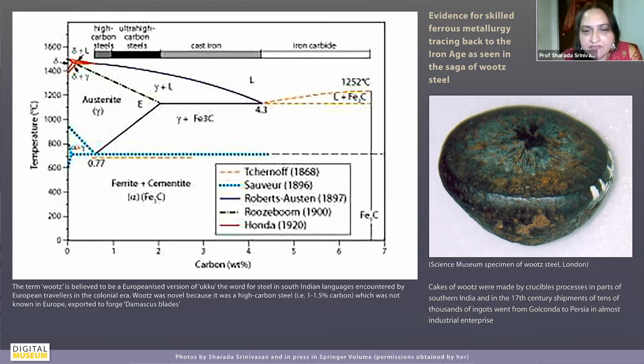Now, I've put in this phase diagram, the iron-carbon phase diagram, more to explain to you that when we're talking about wrought iron, we're talking about an alloy which has very little carbon, less than about 0.04% carbon. And I didn't put this photograph in here, but of course, you would all be familiar with the spectacular Delhi iron pillar, which is one of the largest massive iron forgings in the world. But when we talk about steel and high carbon steel, basically the addition of carbon to iron made it harder and harder. And now in general in the world, we use mild steel, which has less than about 0.4% carbon.